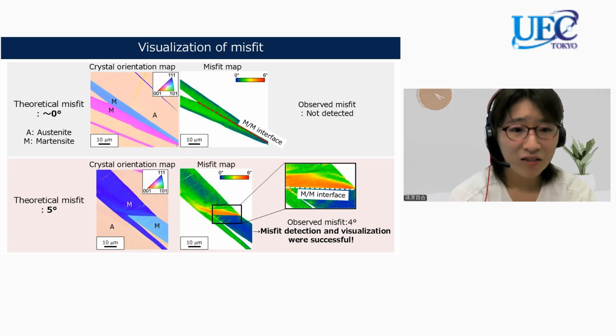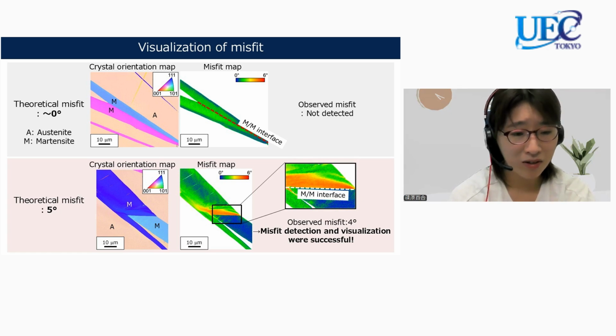Finally, we succeeded in misfit visualization in the observed microstructure. These are martensite plate pairs with a small and a significant theoretical misfit. This pair has almost no misfit at the martensite interface. In contrast, misfit is present for the pair with significant theoretical misfit. The misfit decreases away from the interface.